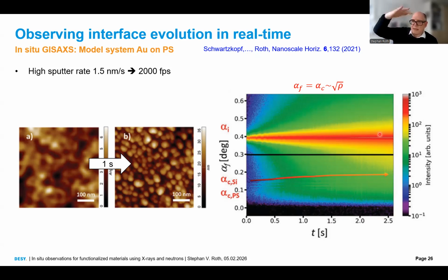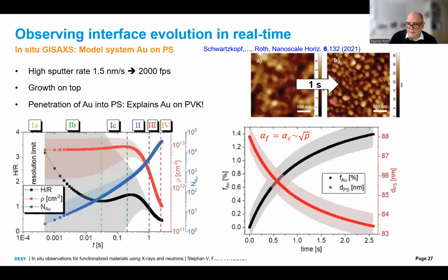You could argue that the gold goes fully into this film of 100 nanometers or 80 nanometers. You could say it stays only on top. You could assume a swelling of the film. We can exclude all this via the simulations, and therefore, using this formula, as I said, we follow the remaining polystyrene layer thickness and the loading. As I said, we know the XRR, so we don't need to cut our sample. And I'm not sure how you would measure such a small loading with electron microscopy.